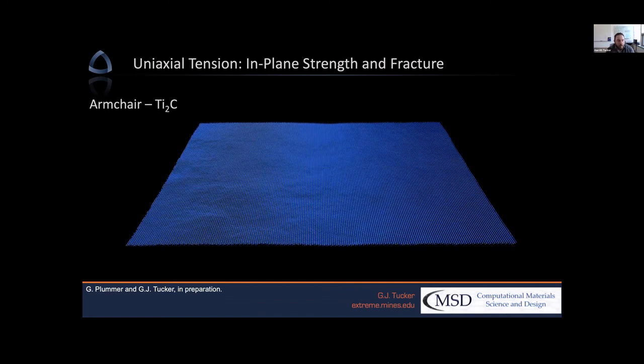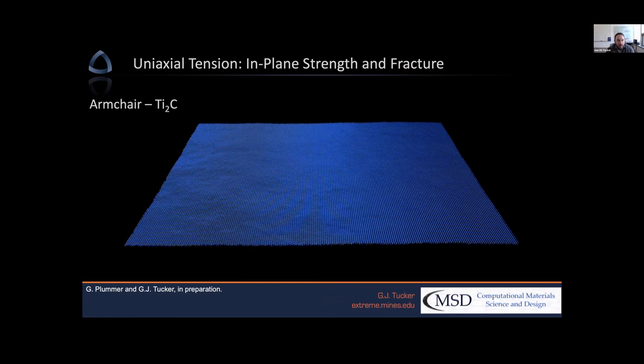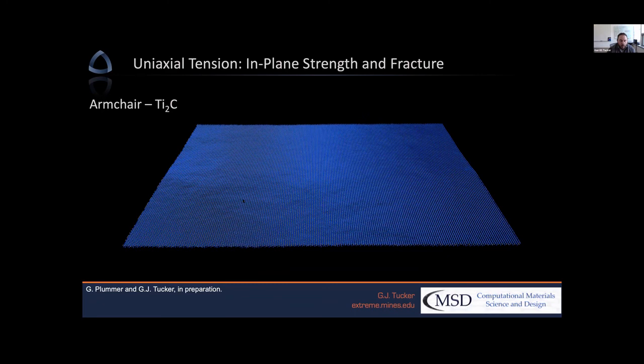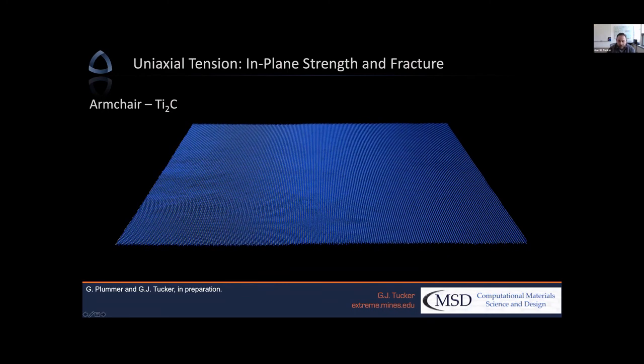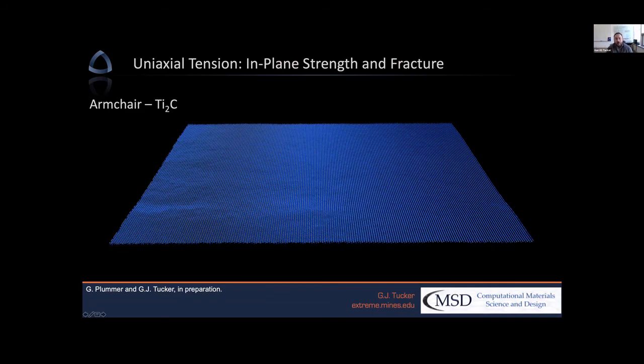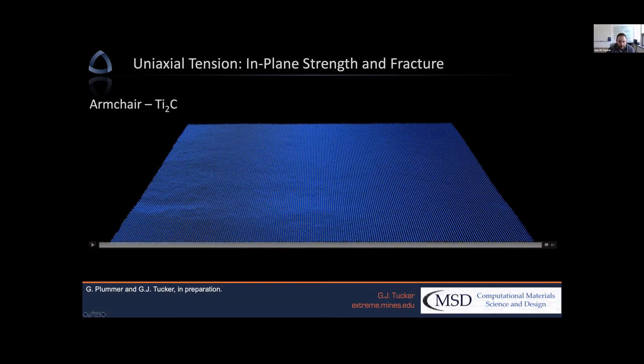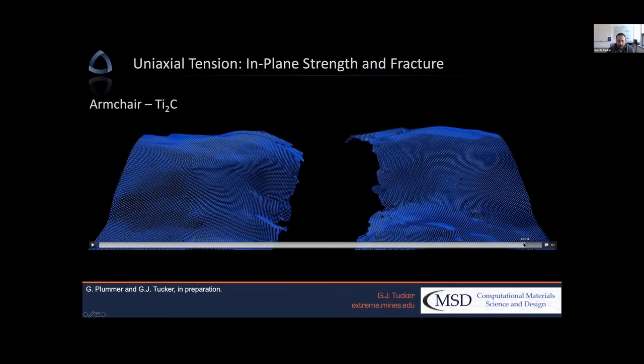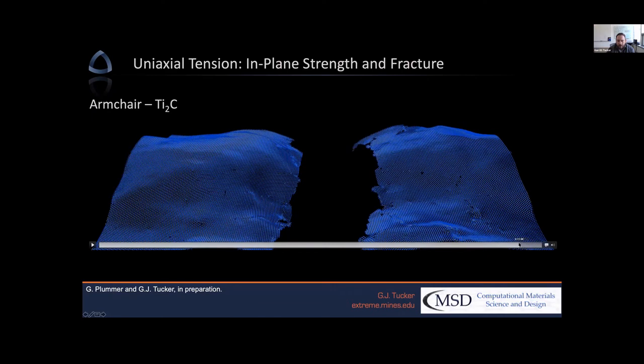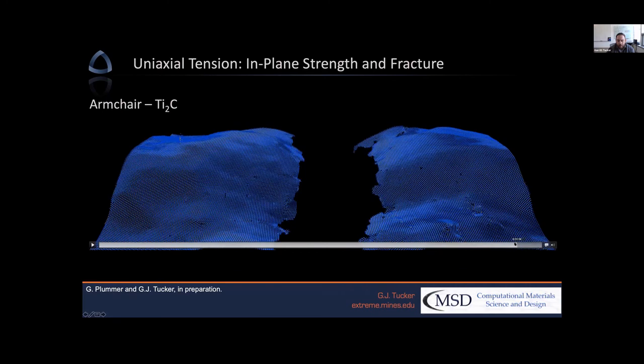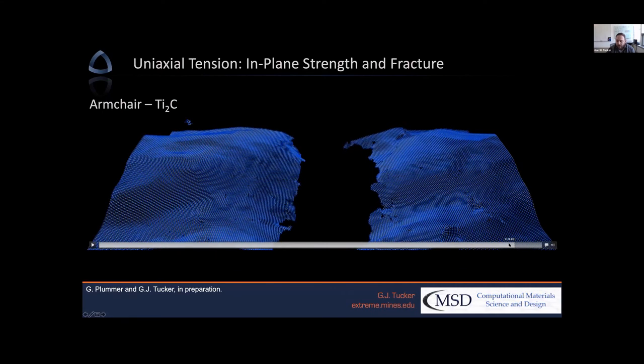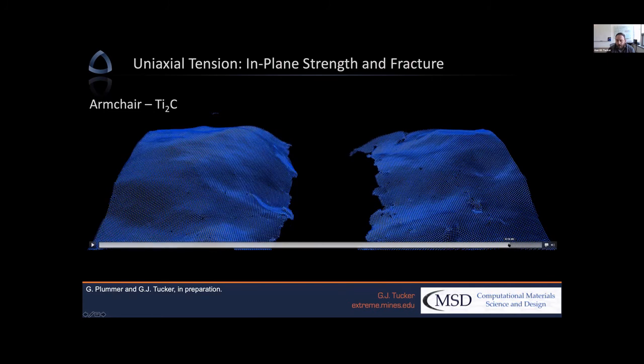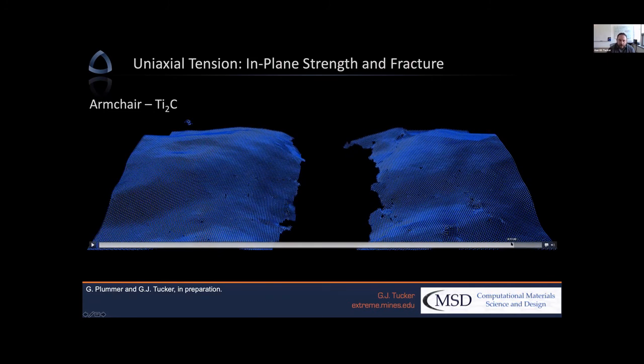So here's a movie of the armchair configuration for Ti2C. And I hope this works over the Zoom. But what you see is we're pulling from both left and right directions outward. And then eventually this thing will break. Yeah, so we can see the breakage right here. And so if we were to go back, we can actually start to isolate some of these states prior to breakage, because we have all of this information, and we can start to understand those fundamental mechanisms which lead to fracture. But you can see here, right here, we get a clean breakage perpendicular to the direction at which we pull on this MXene, which could be logical in a way.